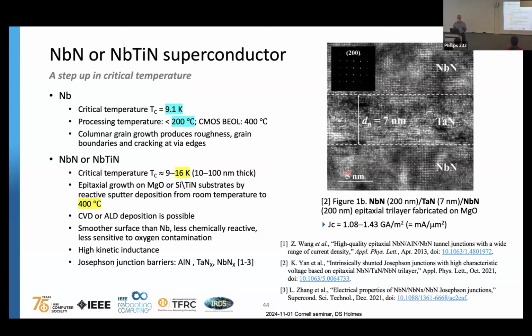The coherence length, the distance within which superconductivity can be destroyed, is on the order of 5 nanometers. That means that interfaces are very important. You have to have good, clean interfaces. And so it's more challenging with niobium nitride or niobium titanium nitride. So we're working on a process. We are developing a process. It's like going back to the drawing board and saying, okay, what materials can we use? How can we do it?